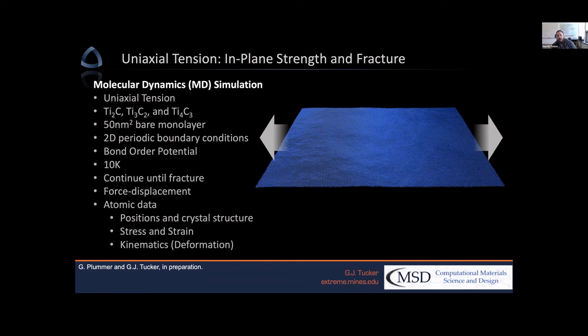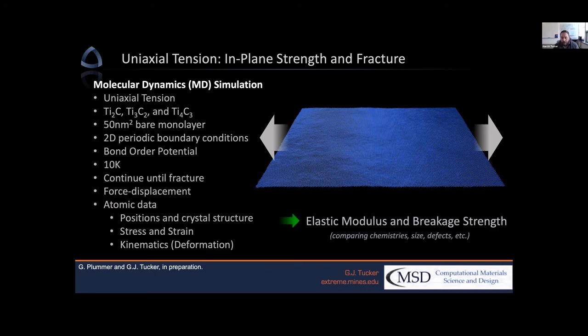So the next thing we want to do is look at in-plane strength and fracture, moving away from nano-indentation and thinking about uniaxial tension. Now, like I said, this is kind of repeating, but builds on some previous work that's been done in the field as well. So here we use a 50 nanometer by 50 nanometer MXene sheet and pull on it until we get fracture. And here too, we want to output the role of different things on elastic modulus and the breaking strength or fracture strength of the MXene.